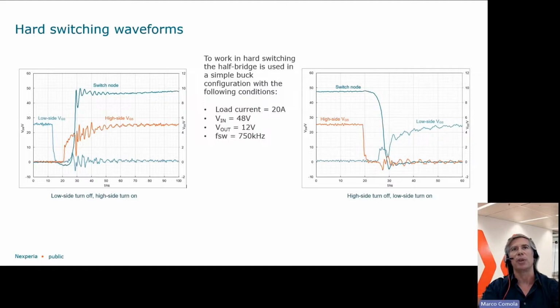So with another switching waveform, again we use it as a buck converter, from 48 volt to 12 volt. The switching frequency set for this kind of measurement was 750 kilohertz, and the load current was 20 amps. The exercise was just to let the board work in hard switching, to let the device work in hard switching. We have the screenshots of low side and high side: low side turn off and turn on, and the same for high side turn off and turn on. You can see how clean the waveform is. There is no oscillation, or quite limited, so the board in this condition is working properly. And this is the message that I want to share with you.